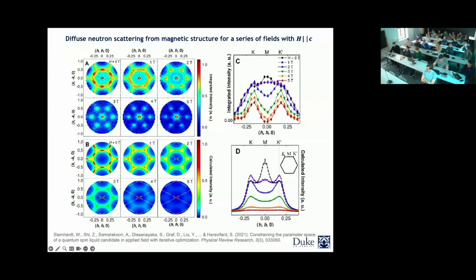I'm sorry, may I ask a question about that? If it were really ordered, then you would expect to see Bragg peaks at the M point? Yes. And so what's observed here is an enhanced intensity, but not a Bragg peak. But not a Bragg peak. Very diffuse. Yes, that's right. Which, from different models, somebody would say that you see this diffuse scattering, but it is practically coming from the spin on the Fermi surface.